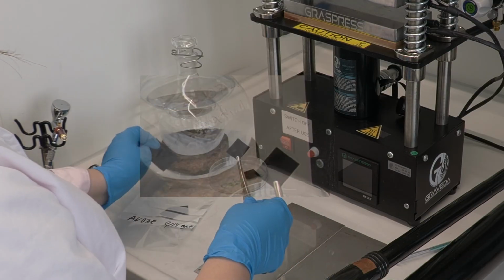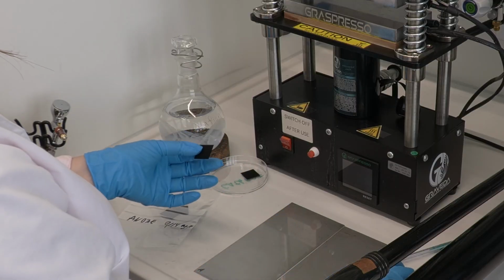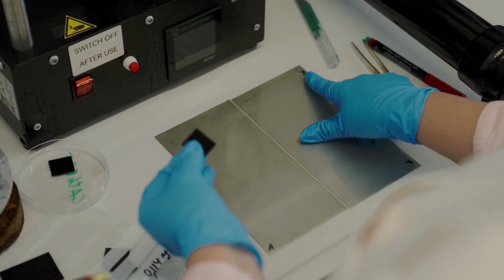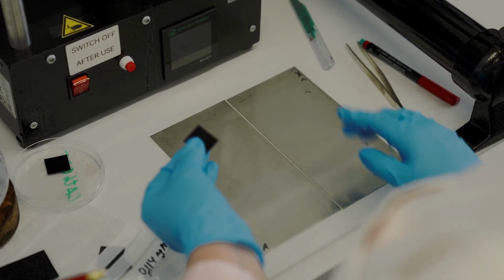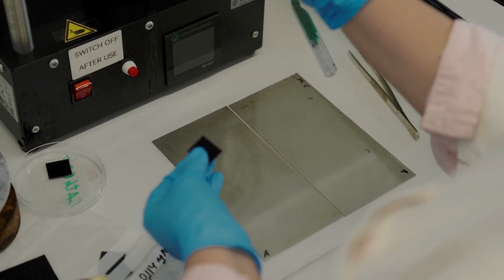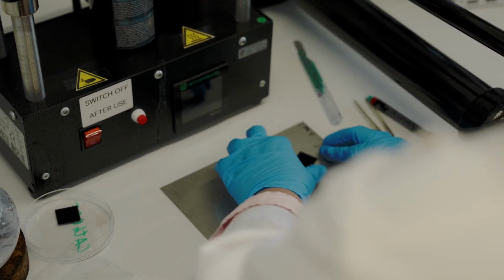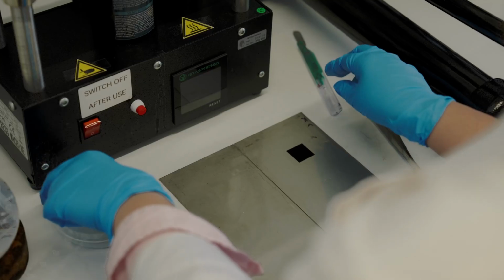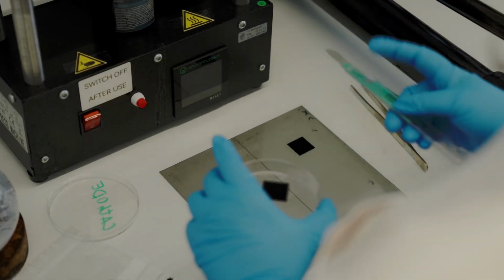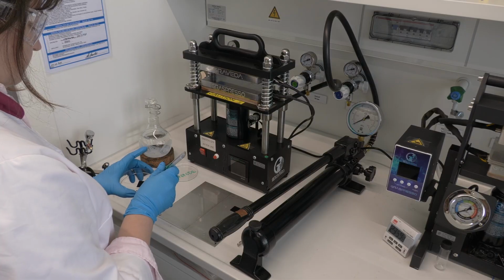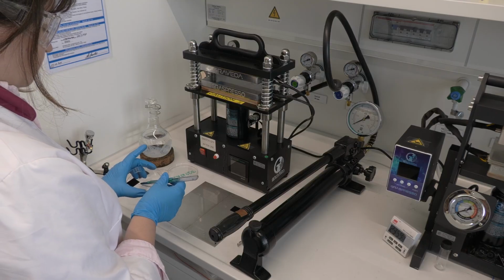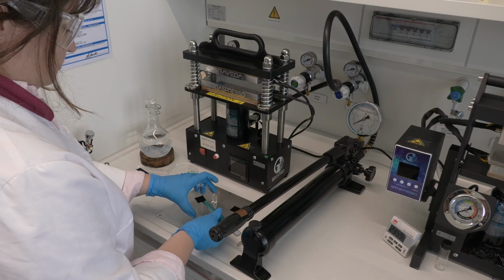First, we assemble the membrane electrode assembly on an alumina substrate. We use clean alumina plates marked K and A for the cathode and anode respectively. There are also left and right positions in the press. The assembly sequence is as follows. Place the cathode, 2 samples if you need to prepare 2 MEAs.